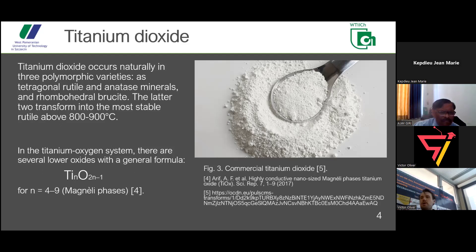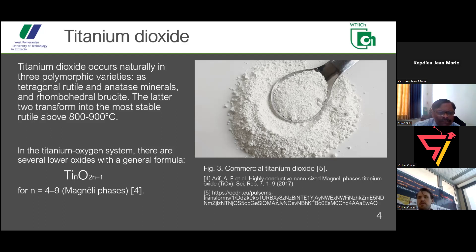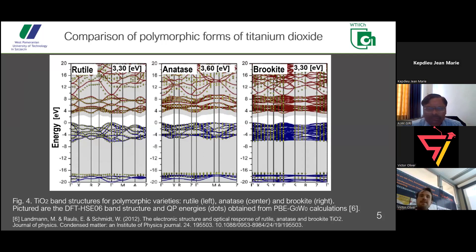Reduction is basically absorbing electrons, taking electrons, and this half-reduced state really allows electrons to be trapped inside and then given to the CO2 molecule, which is very difficult to reduce because of the double bondings. Regarding titanium dioxide, we have three phases — three possible crystallographic structures: rutile, anatase, and brookite. This handy graph shows the differences in terms of conduction and valence band between them.